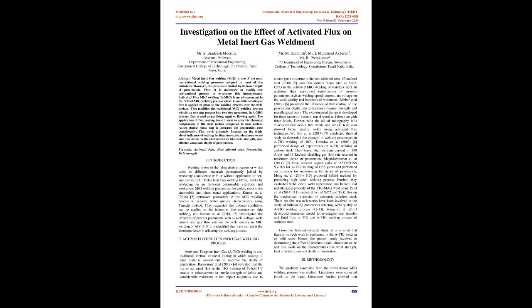2. Activated tungsten inert gas welding process. Activated tungsten inert gas, A-TIG, welding is also a traditional method of metal joining in which coating of base plate is carried out to improve the depth of penetration. Premkumar et al. 2018, reference 4, revealed that the use of activated flux in the TIG welding of Ti6Al4V results in enhancement in tensile strength of joints and considerable reduction in the impact toughness due to